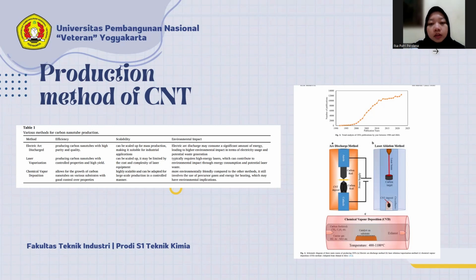A longer reaction temperature can increase the CNT yield. Munoz et al. found that the amount of SWCNT product was very small when using helium gas, whereas they stated that SWCNT yield was higher with the use of argon and nitrogen.